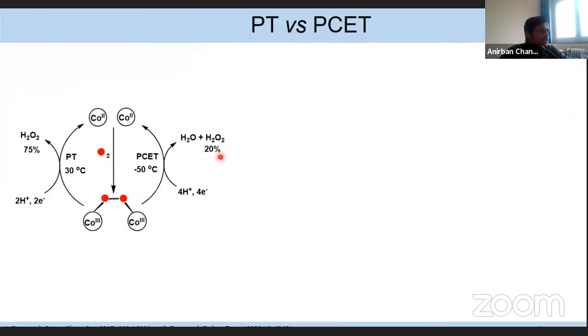So from this experimental observation, I propose this catalytic cycle where cobalt 2 species first react with oxygen to form a dinuclear metal peroxide species. Now this dinuclear metal peroxide species at high temperature goes via proton transfer process in presence of proton to produce hydrogen peroxide, and electron is required to reduce the cobalt to cobalt 2. Whereas at low temperature, at minus 50 degree centigrade, it goes via proton coupled electron transfer process to produce water.